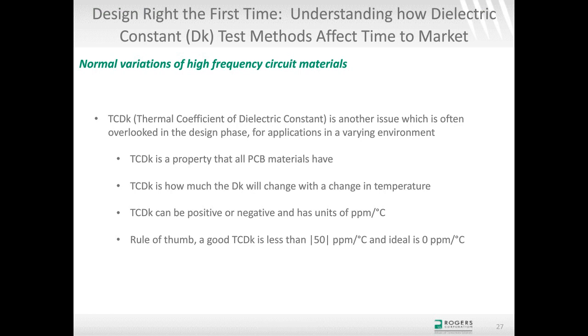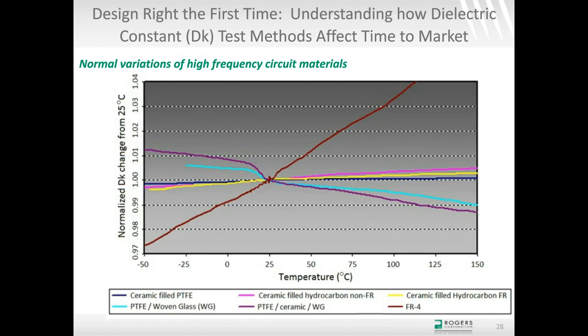So here's a chart that is looking at the TCDK behavior of several different materials. And to begin with, I'll look at the purple curve here. The purple curve, you can see, has a pretty good transition around room temperature changes in temperatures, and that's actually normal for a PTFE-based material. If we were showing a pure PTFE-based material, this curve around room temperature would be exaggerated much more than this. And then the light blue curve just below there, you can see that has less effect, or it is less affected by room temperatures anyway, and that's just due to differences in formulations that we know how to control.